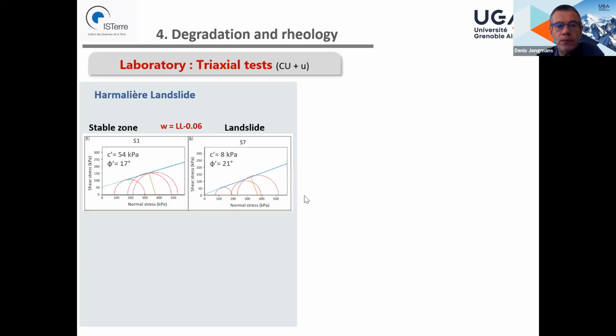So for the triaxial tests that we performed on samples from the stable zone, the escarp, and the landslide, we have the comparison between the 2. The striking result is that we have a decrease in cohesion from 54 to 8 kilopascal, maybe with a slight increase in the friction angle.